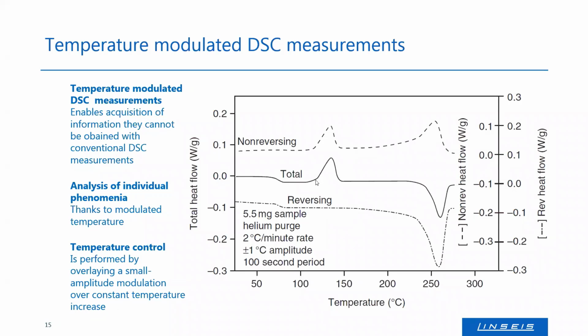But what about the rest? So the non-reversing heat flow, of course, we could see here the recrystallization, but there's a second transition here in the range of our melt. And we cannot see this in the total heat flow, but if we check the reversing heat flow and the non-reversing heat flow, in the reversing heat flow, the melting peak looks much bigger than in the total heat flow. So this melting peak is overlaid by a second exothermal reaction here, and this information we just can get through this temperature modulation.